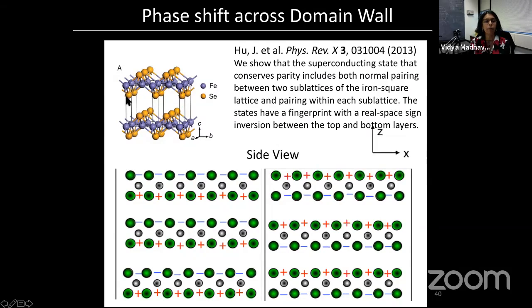The interesting thing about this compound, like I was mentioning before, is that these are the top selenium/tellurium atoms. These are the bottom ones. They're shifted from each other by half a unit cell. So when the crystal forms like this, it picks that these would be at the top and these would be at the bottom, because you can imagine that the crystal could have also formed with the top selenium atoms being here and the bottom selenium atoms being here. Because there are these two possibilities, you can imagine that in a normal crystal growth process, you might have regions of this phase, and then regions where the crystal is phase shifted just a tiny bit in terms of where the top and the bottom selenium atoms are.